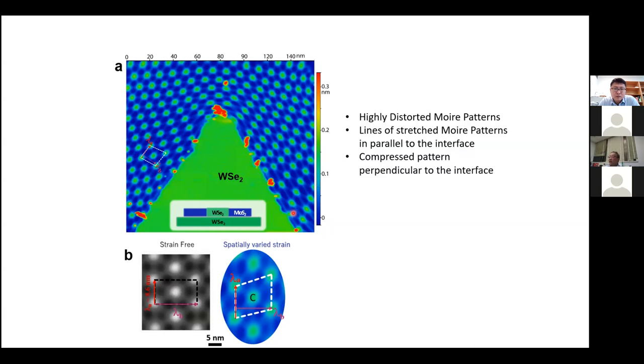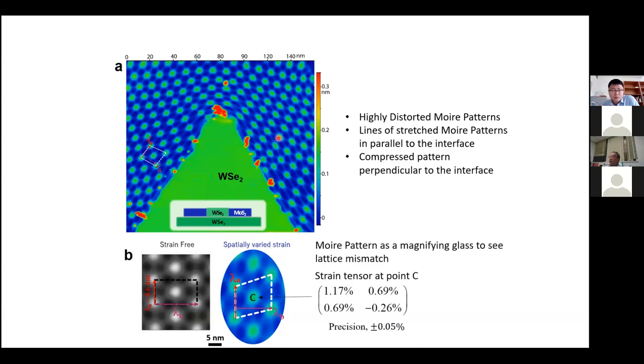This also makes sense because if you think about it, in order to maintain this coherent strain at the interface, the MoS2 will have to be stretched parallel to this interface. But as a result, perpendicular to this interface, the material will be compressed. And then since the strain is going to have a gradient, automatically there will be a shear strain that comes with it. I won't go into the detail, but using this moiré pattern, you can determine the strain tensor very precisely.